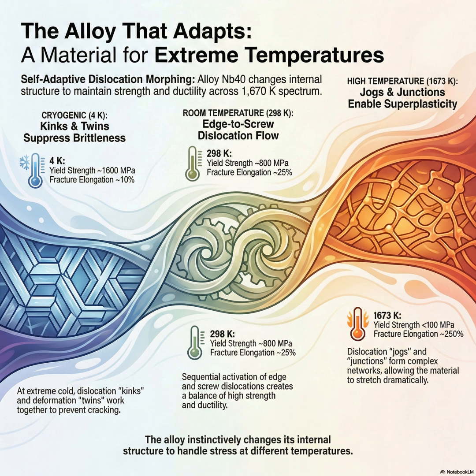Tiny hiccups. But when these jogs on different dislocations interact, it's crucial. They lead to the rapid formation of stable junctions. This is where two dislocations essentially merge to form a third, more stable defect. So it's building up this complex internal network of defects. Why doesn't that just cause it to fail?